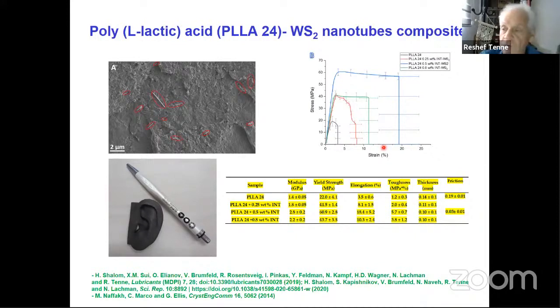The other advantage of tungsten disulfide nanotubes is that they do not agglomerate very strongly because they don't have the pi-pi stacking like carbon nanotubes or like graphene. Graphene has a lot of pi forces due to the aromaticity of the layers. They stack very much and they agglomerate, and it's difficult to separate them. If you separate them, you have to invest energy, and then you ruin your material, or you find a smart way to separate them by surfactant. And then the question is whether the surfactant affects the interface with the other matrix.